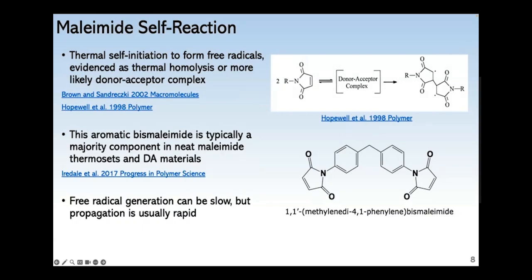So the maleimide self-reaction can happen because they thermally initiate themselves to form free radicals at high enough temperature. Electron spin studies showed that this probably occurs either due to thermal homolysis of this carbon-carbon double bond here, or due to a donor-acceptor complex between two maleimides. And this particular bismaleimide that I'm showing here, I also used for many of my studies, and it kind of worked out favorably because this is a majority component in most neat maleimide resins and DA materials that are studied industrially and academically. Then my last comment here is that sometimes free radical generation can be slow, but almost always the propagation is rapid. And I think some of my results today will attest to that fact.